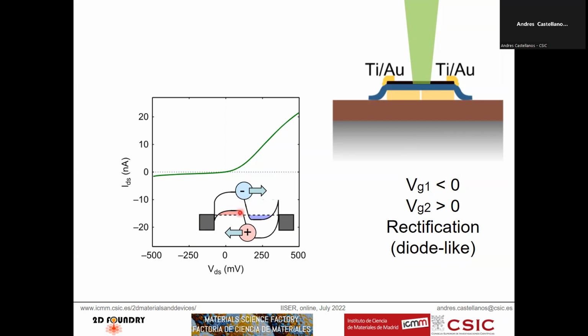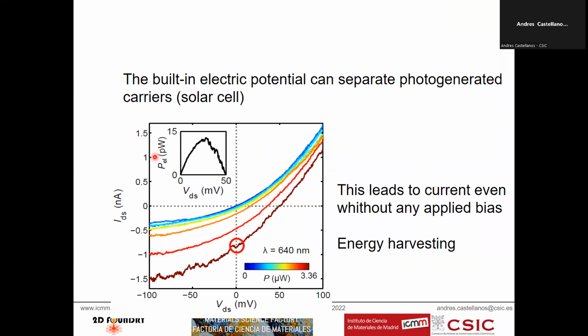And this electron and hole feel the built-in potential that we have here. So basically they get separated, even without applying any voltage. So basically we are creating a tiny solar cell out of this black phosphorus. And indeed, if you study the current versus voltage characteristics of the device as a function of illumination with higher and higher power, you see that you start first with this rectification curve here, and you start generating current even at zero bias.